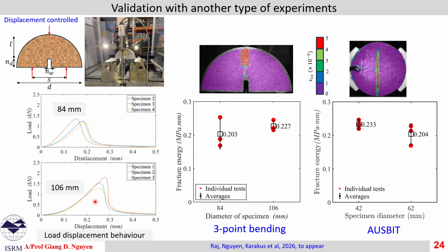The area under the curves in the 2 cases is used to work out the fracture energy, and in this case, we have very close results. This 3-point bending test is giving us that much fracture energy, and our technique here is giving us that much, and they are very close to each other. So which indicates the reliability of the proposed test using lateral displacement control on Brazilian disk.